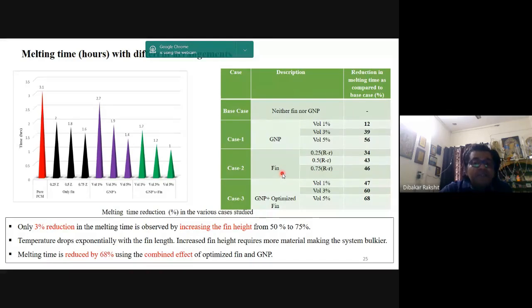And when we are having these fins, how much effect in the reduction of the energy storage device is happening by having the fin heights from 25% of the annulus to 3/4 of the annulus structure. How much effect is happening on the melting time, that also we studied. And then in combination of the GNP and the optimized fin, whatever we have achieved, as I told, between 50 to 75%, above 50% it is good, but beyond 75% it is not good. So after finding that optimization, the optimized fin, how this reduction in the melting time can be reached utilizing graphene nanoplates in their various proportions by volume, that also was studied.